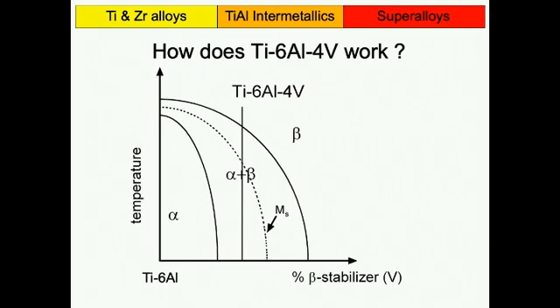What is important though is that if you now assume that this is where we have our titanium 6 aluminum 4 vanadium, and we are in the two-phase regime, as we heat up, we start changing the volume fraction of alpha and beta phase. Okay, and that's something I want you to understand. It's not very noticeable up to maybe temperatures of 700 degrees C, but further up you start to see it clearly. The line is fairly vertical initially, and then it starts bending over, and that means you start to get more and more beta phase at fairly high temperatures.